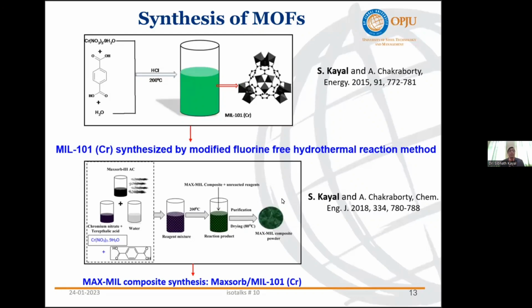Also, we have prepared a composite, that is MIL-101 chromium using MAXSORB. MAXSORB is a commercial activated carbon material that we used to make a composite material. So basically, we have prepared it by the same method, but we have additionally used this adsorbent material in the precursor materials, and the rest of the procedure is the same.